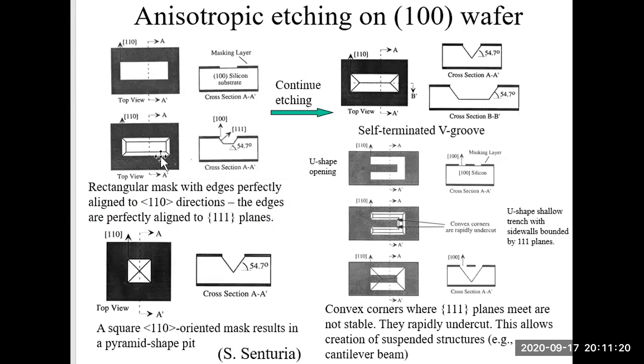So after we start anisotropic etching, those four 111 planes will emerge immediately. After etching for a while, the rectangular opening results in a cavity with four slanted side walls formed by 111 planes. As I said, 111 planes are virtual stops in anisotropic etching. They will stop the etching, so they will emerge. This is a cross-sectional view of the cavity. The slanted side walls are 111 planes, and the angle is 54.74 degrees. Questions?